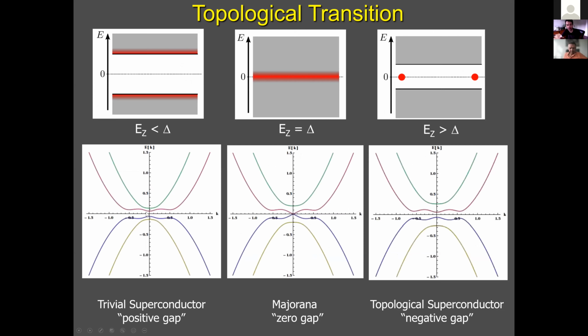So you can see if magnetic field is 0, these 3 gaps are the same at Fermi momentum minus, at 0 momentum, and at plus. These 3 gaps will be the same if this Zeeman energy is 0. They're just equal to the superconducting gap. And then when we start applying magnetic field, we start closing the gaps. But we only close actually the middle gap at k equals 0. We just start closing it because spin up and spin down split.